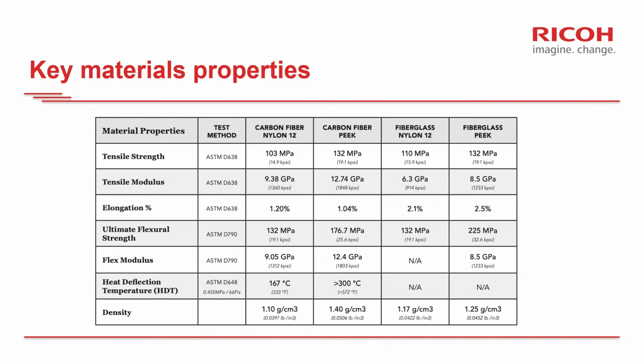And as Mark mentioned before, the very high strength-weight ratio for these materials make them a really good solution for metal replacements, more in particular for aluminum alloys. Talking about PEEK, which is also generally a material that is quite difficult to print, for me, it's a great material because it has a lot of benefits. In particular, a very high temperature resistance and dimensional stability at high temperature, as the melting point of the grade that we use in this technology is around 340 degrees. And combined with these properties, PEEK also has excellent chemical resistance, very good wear resistance, very good insulating properties, and it is also intrinsically flame retardant.